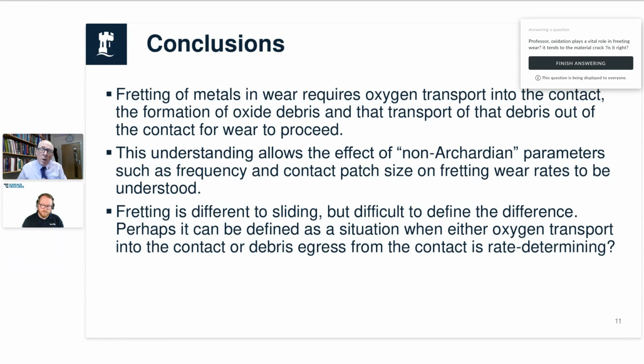Quite often, if you've got a lot of oxidation occurring in a fretting contact, the level of subsurface damage can be quite low. One of the questions you've got to ask is, are we more worried about the wear, essentially the loss of dimension, which might lead to problems in a structure, or are we worried about subsurface damage, which you would look at and say, well, this is going to be a fatigue issue. So one needs to say, what are the big issues here? But I wouldn't say that oxidation or oxide itself necessarily tends to form cracks within the structure.